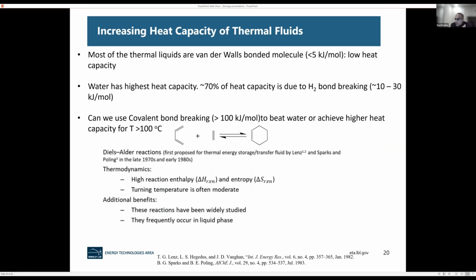So they have very low heat capacity. Mineral oil has a very low heat capacity. Thermal oil has a very low heat capacity. Water has the highest heat capacity because 70% of the heat capacity in water is because of hydrogen bond breaking, 10 to 30 kilojoule per mole.